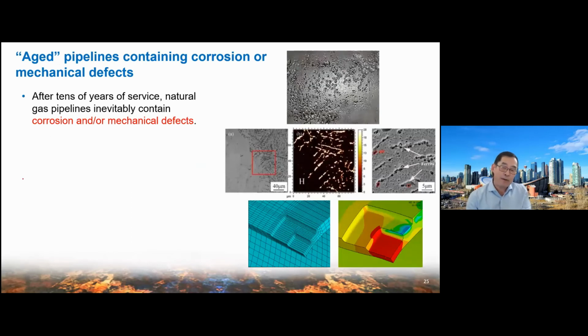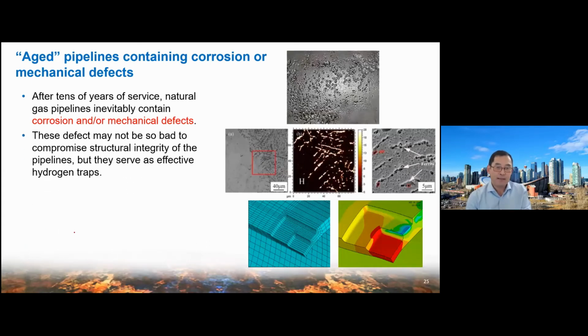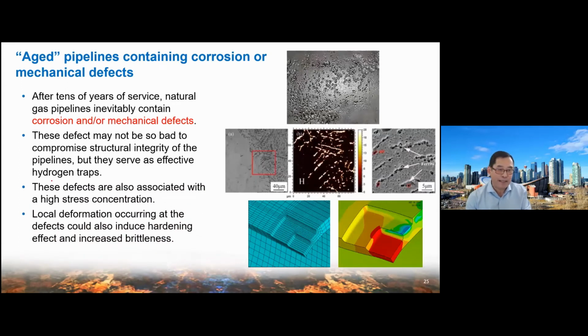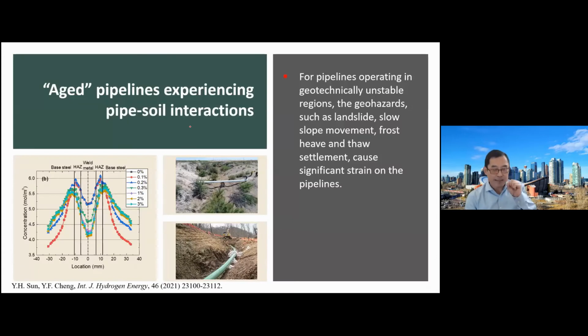First one, after a pipeline has served in the field for many years, there must be loss of metal from corrosion and mechanical defects. These defects are probably not so bad in terms of pipeline integrity. The pipeline can tolerate this kind of corrosion or mechanical defect, and the pipeline can still operate. However, these defects are very effective hydrogen traps. So for the aged pipeline, hydrogen can become concentrated at the corrosion sites and the mechanical damage sites, such as dents and other metal loss sites. These sites can accumulate high hydrogen to cause hydrogen embrittlement. So that's the first extra challenge.